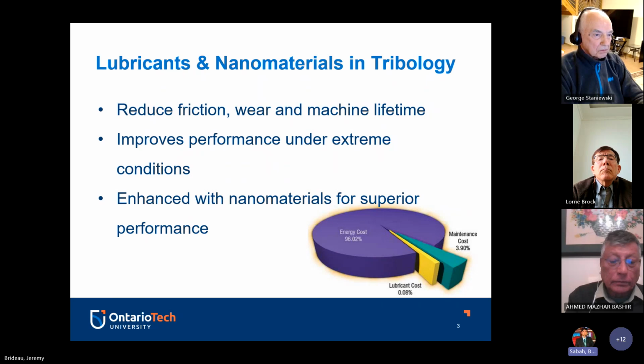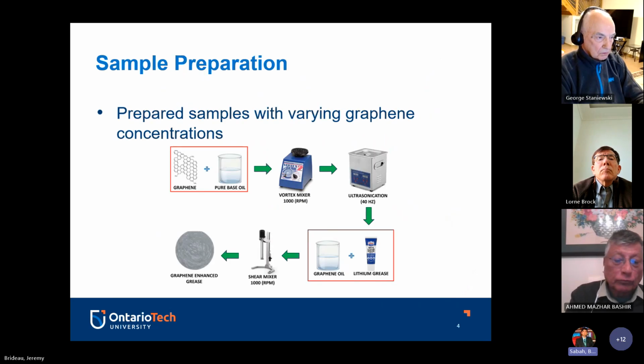But how do we do this? The first step is we prepare different samples. If you look online, there are several different methods used to prepare graphene-enhanced grease samples. However, there's not one clear and obvious method to choose from. During my research and my time working on the master's, we were able to perfect a way of mixing the graphene into the greases.